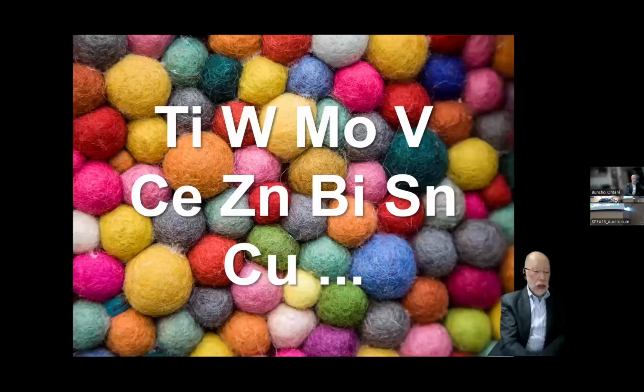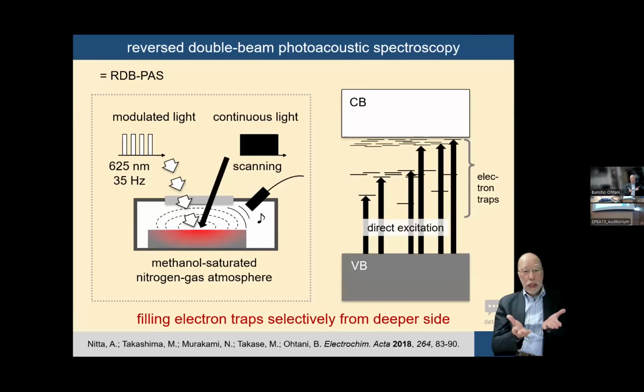And if that is measured easily, it gives the information. So then we prepared a new methodology, reversed double beam photoacoustic spectroscopy. An electron trap is a vacant electronic state in metal oxide powders, and an electron in the valence band is directly excited to electron traps to fill up the electron trap with electrons, and this changes the color of the sample, and this change of color is detected by photoacoustic spectroscopy.